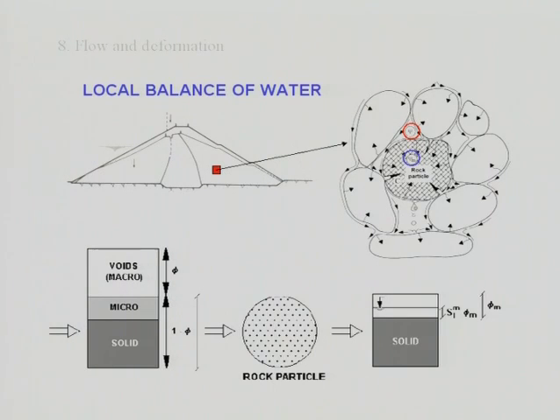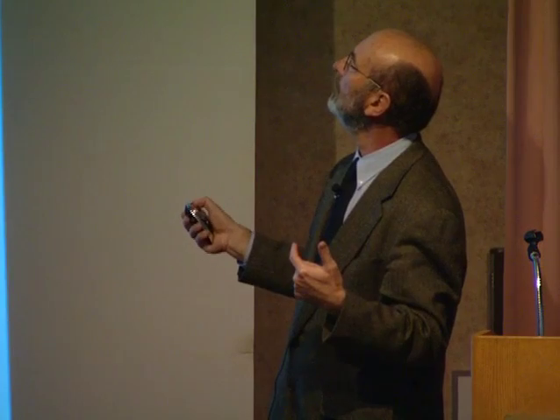But this is a very complicated material. So you have, as I said before, a small porosity in the rock, small pores, and then we have the big voids in the rock fill. In a state of lack of equilibrium, probably, we may define two energies of the water, or two suctions, if you like. One prevailing at the big pores, and the other one at the small pores. The porosity is so different that probably the material can sustain those different suctions for a while. Of course, it can equilibrate.